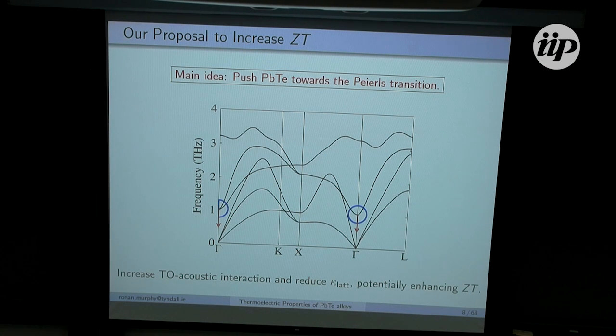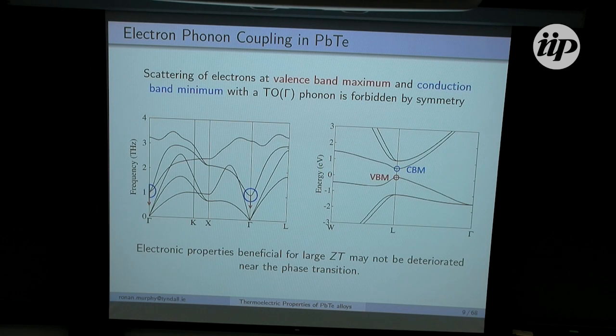But as I mentioned earlier, in the thermoelectric figure of merit, we have some other properties that we have to take into consideration as well, such as the electronic properties. Now, this is maybe a little hand-wavy, but I have here the electronic band structure of lead telluride. If you just focus here on the valence band maximum and conduction band minimum, it turns out that scattering of electrons by a TO mode phonon at the gamma point, from these two points, is forbidden by symmetry. So this gives us a little bit of a hint that as we begin to push lead telluride towards the phase transition, softening that TO mode, the electronic properties may not be that negatively impacted.